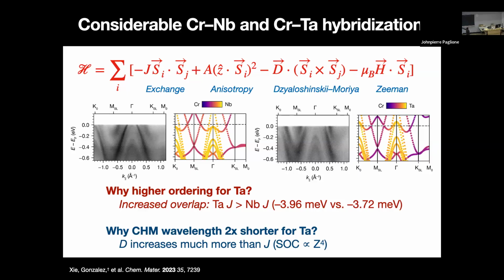And then why is the wavelength of the chiral helimagnetic winding shorter for tantalum? Well, J, the magnetic exchange, has gone up only a little bit between niobium and tantalum, but D goes with the spin orbit coupling, which goes as basically Z to the fourth, the atomic number to the fourth. So that D term has increased a lot more in going from niobium to tantalum than J has, and so it is able to outcompete and tighten the winding of these systems.